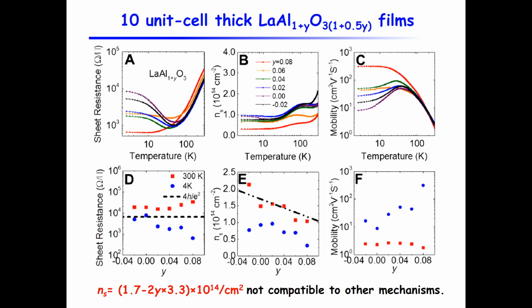Nevertheless, what we're showing is that if we grow these lanthanum aluminate layers at higher oxygen pressure, without indications of oxygen vacancies, then we can get this kind of dependence of the carrier density on the stoichiometry of lanthanum aluminate, not only qualitatively, but quantitatively. And we think that this is pretty strong support for the mechanism of electronic reconstruction.